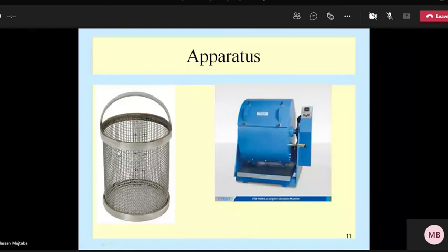Because if aggregates absorb water or have affinity for water, then a phenomenon called film stripping occurs: when they absorb water, they are going to remove the bitumen film coating around the aggregates, and the aggregates are surrounded with water. To avoid that, we use aggregates whose water absorption is less, normally 4% is the upper limit. So in this one test, you are going to determine three specific gravities and one water absorption.